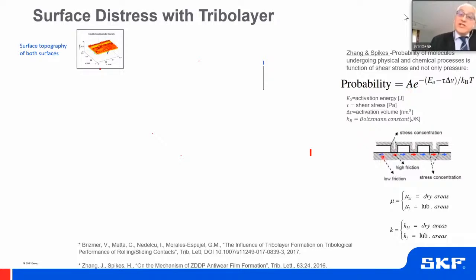And then you will generate a patchy tribofilm, as indicated in this very rough diagram, where we see areas which are separated by the lubricant, and then we see areas which are more kind of dry contact. And therefore, we have locally different friction coefficients and different wear coefficients, because it can be the case that you have a dry contact between tribofilm and tribofilm, or tribofilm and steel, or steel and steel. So you need to be able to measure these friction coefficients and wear coefficients in the experiments in the lab. But once you have that, then we can use this model.